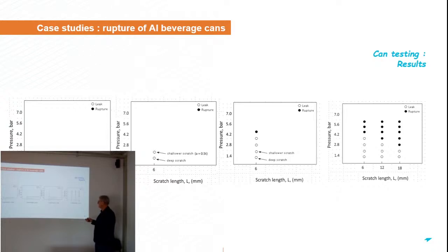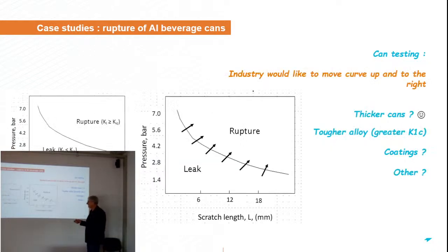Then we did this test for different scratch lengths, increasing from 6 millimeter to 12 and 18, and again we repeated this same test by increasing the internal pressure. And you can see that we could discriminate two domains where you have leak below and a rupture above this line here. Here you have the stress intensity factor lower than the toughness of the material, and here you have the stress intensity factor higher than the toughness of the material.